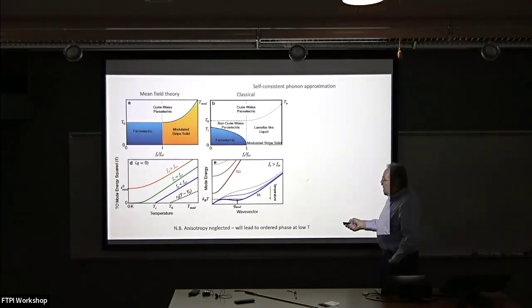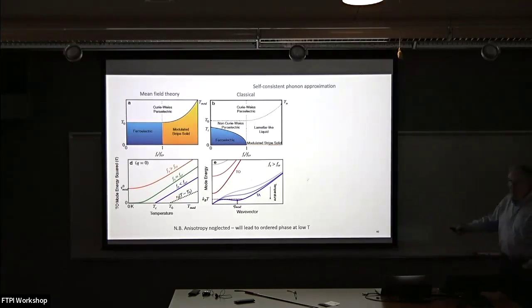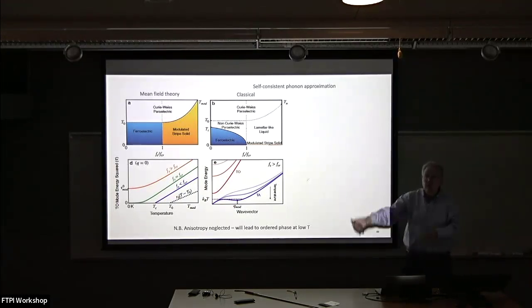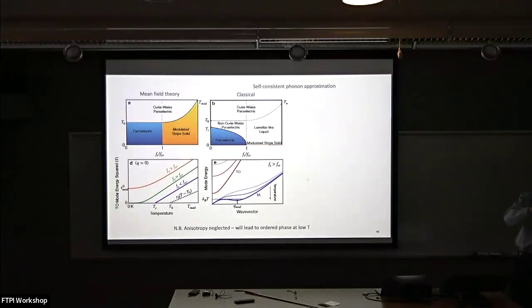So here the point is again relatively trivial. Suppose I'm in a situation where this mode goes soft at some finite Q. The theory I gave you, and actually in practice, because I'm at such very long wavelength, the system is going to look isotropic. So what I know from this is that I'm supposed to get some modulation wave vector at some amplitude Q, but I don't know the direction it's going. So that's a vector which has to find its way on the surface of a sphere in a three-dimensional system. And actually, in a d-dimensional system, it has a d-1 dimensional space to fluctuate in. And that means you add any thermal fluctuations to that, and it will destroy the order, and it'll become a nematic lamella.